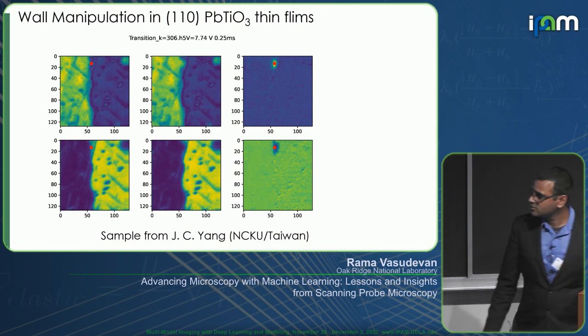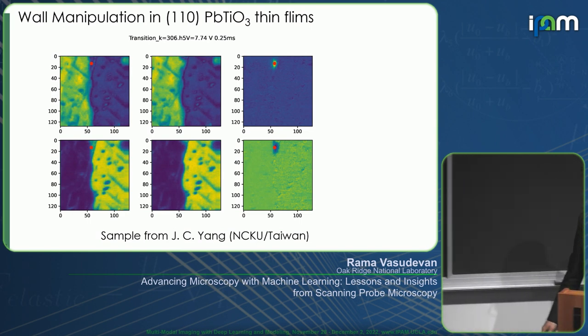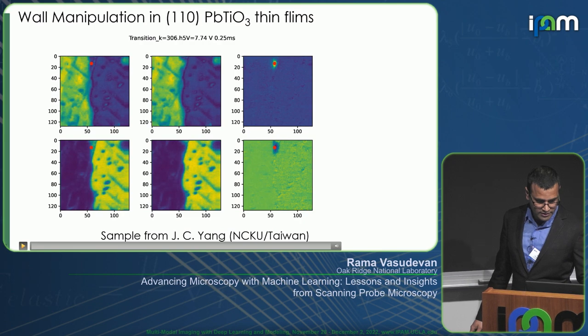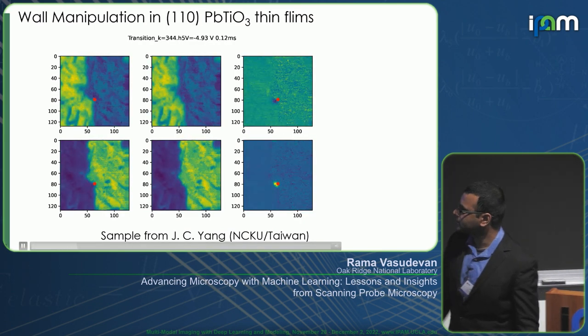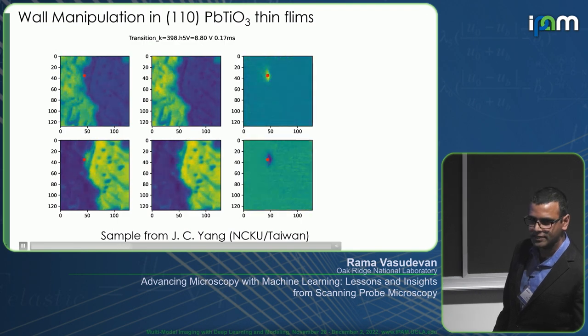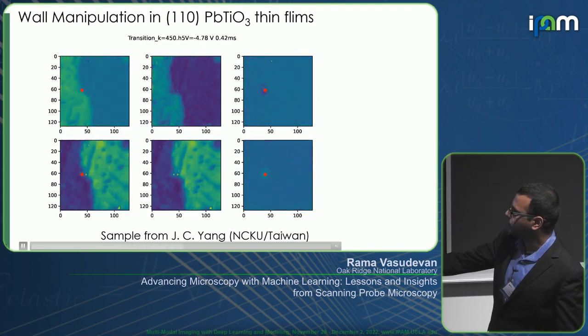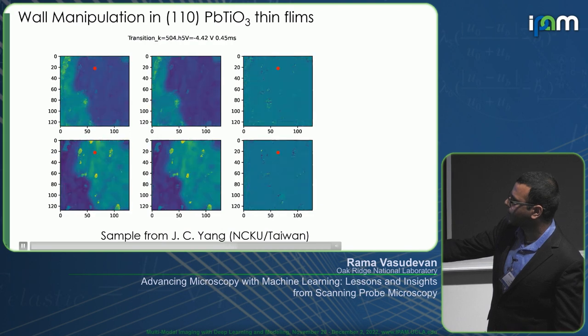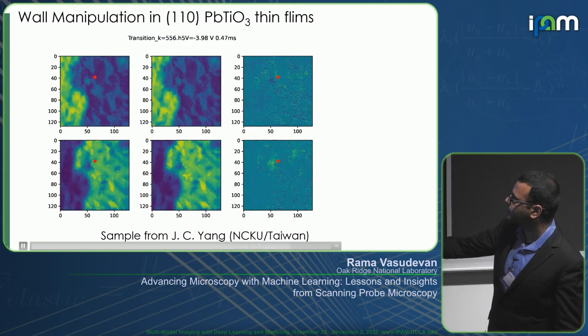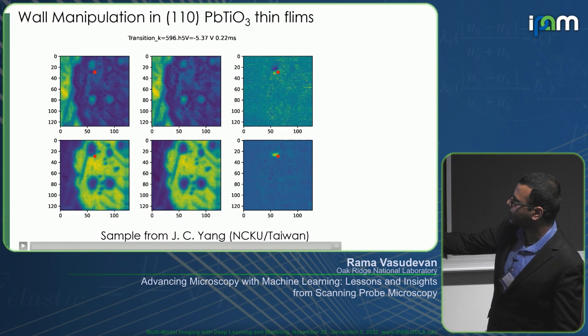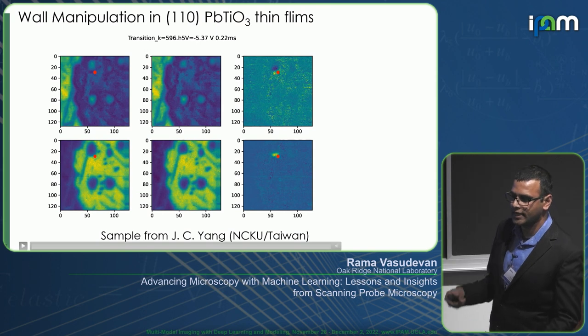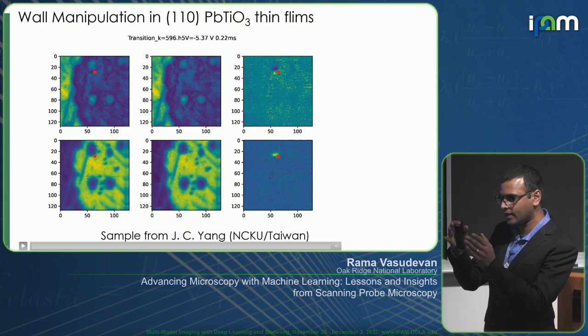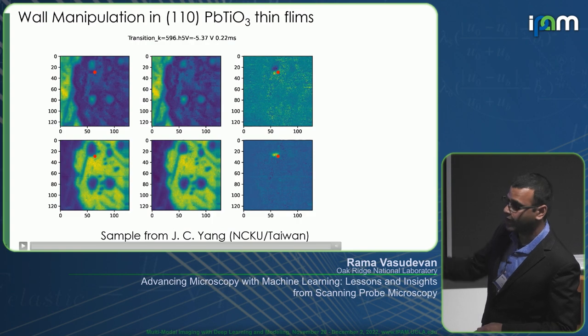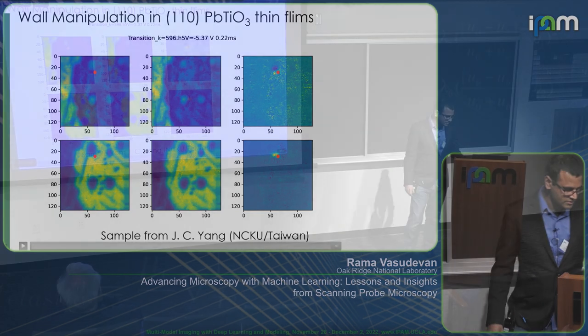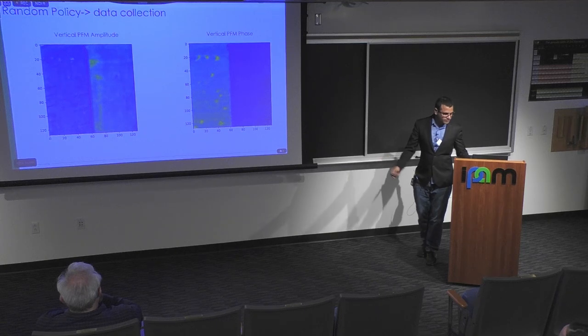And so here is an example of data that I collected last week. This is sped up data, which took 2 days to collect, but this video is a speed up. What we do is we allow the instrument to find the domain wall and apply voltages of random pulse widths and amplitudes to the domain wall and then image the result. So what we get is the previous wall position, the action that we applied, and then the next state.